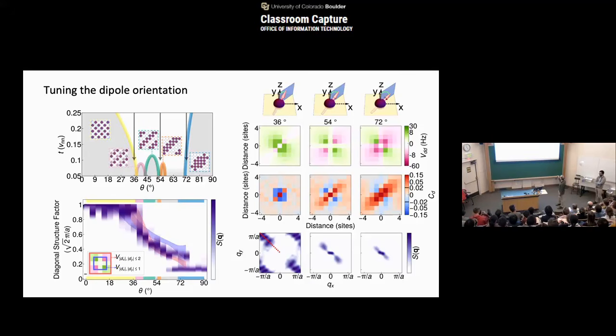And then this beyond nearest neighbor is repulsive in this direction and attractive in this direction, and that then leads to those stripes, right? So it wants to have the atoms form diagonal stripes, because it attracts them one way and repels them the other way. But it's actually remarkable that we can see that, because this is yet a factor of 3 or so less interaction. So the interaction strength here is less than 10 hertz, right? But yet it can give rise to diagonal stripes. Does that make sense? Is that answering your question? No? Maybe we can move on.